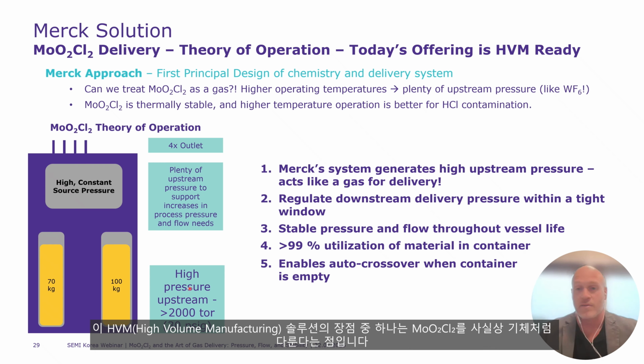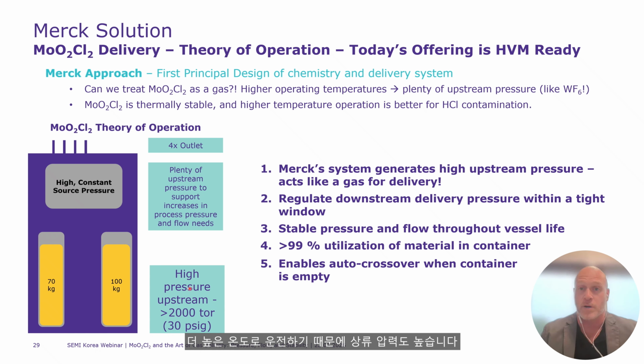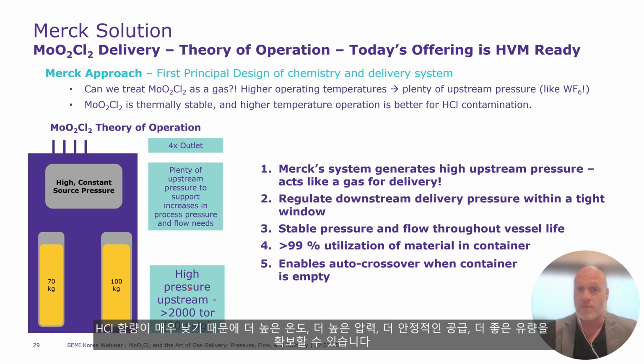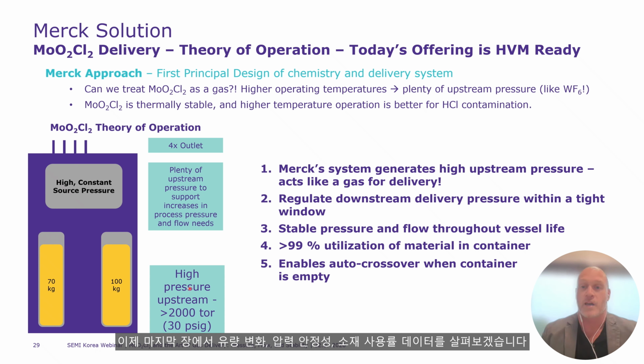One of the advantages of this HVM ready solution is we're fundamentally treating moly dioxide dichloride as a gas. We're going to hotter temperatures, which means higher upstream pressures. So this system operates almost like a gas delivery system. All the simplicity we liked of a gas delivery system is baked into the moly dioxide dichloride delivery system. Our moly dioxide dichloride is a thermally stable molecule. Our material is HCl free. All of that means we can go to higher temperatures, better upstream pressures, better stability, better flow. So let's look at what the flow variation, pressure stability, and utilization look like in the last couple of slides.